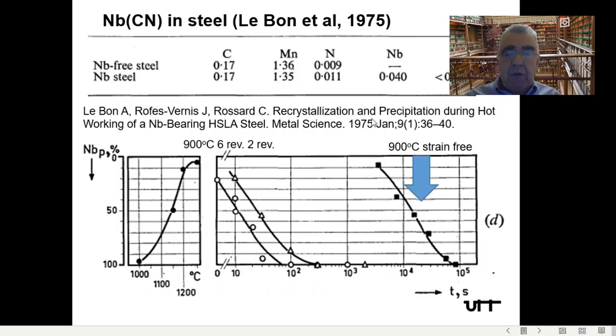So I'm going to show you just one of the adjustments we did for niobium carbonitride with the classical work of LeBon back in '75, because this is not easy. The experimental work is very difficult to do too. So if you look at 900 degrees strain free, and all you steel makers are really interested here when you have niobium precipitation. I mean, this is temperature, this is niobium in solution. So this means that as the time goes here, you have less and less niobium in solution, so you are precipitating. And here is what's happening, how fast you precipitate when you have deformation.